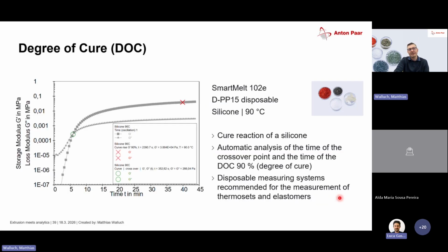Then something else, the degree of cure. So in this case, we do a test with a disposable sample, a disposable measuring system. We have something like a resin that we put on our rheometer. We heat up to a certain temperature. In this case, it is 90 degrees. And we want to know how long it takes for our material to cure. So we just keep everything constant and have a look at what happens over time.